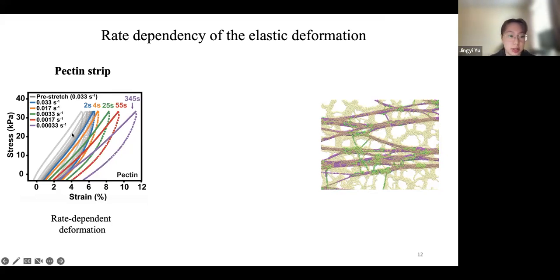You can see here in this test, we pre-stretch the material 6 times to eliminate the plastic deformation, and then we change the stretching speed by 100-fold to see how the deformation would change. You can see that the slower we stretch the material, the higher amount of deformation it reaches, suggesting that the deformation of the pectin is indeed rate dependent.